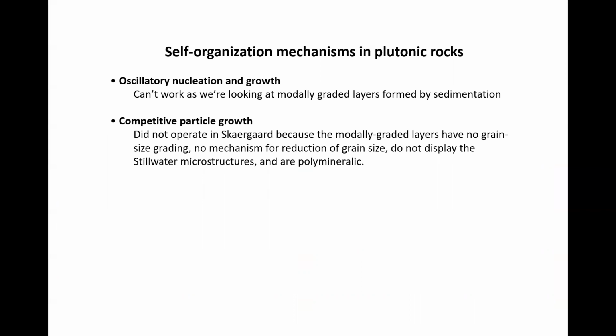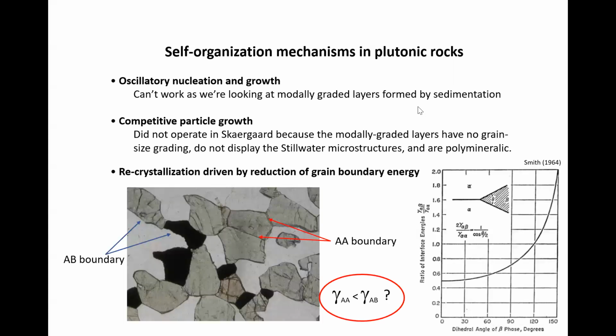It's very notable that the modal graded layers, these metric scale modally graded layers on Skaergaard, have not got a grain size gradient. That's been known for decades and decades. There's no grain size gradient. We've got no mechanism for reducing the grain size so that Ostwald ripening becomes important because it was a closed system, unlike Bushveld and Stillwater. We've not got any of those microstructures indicative of slow cooling and melt present texture equilibrium. It just doesn't work. Okay, so we can't invoke competitive particle growth for the Skaergaard example.